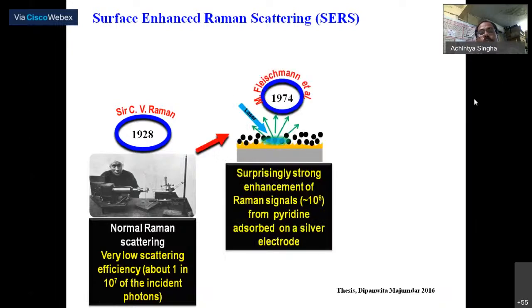Yeah, in 1974, there was a breakthrough. Actually, these scientists, Fleischmann, they observed that if a molecule adsorbs on silver, they did an experiment on a silver electrode with pyridine. The pyridine molecule adsorbed on the silver electrode, and they showed a strong enhancement of the Raman signal. Initially, they thought that this was due to the rough surface of the electrode, because in a rough surface we know the area is large and more molecules are adsorbed on the surface.